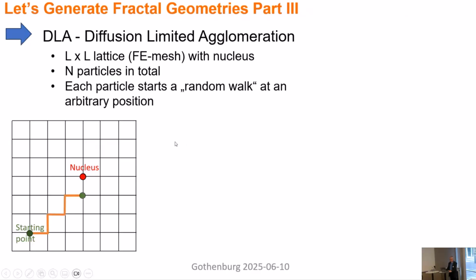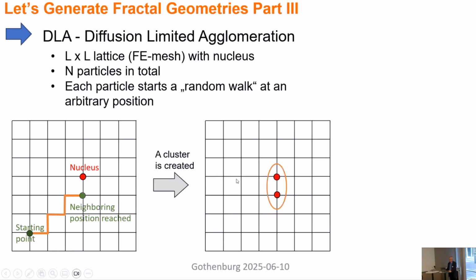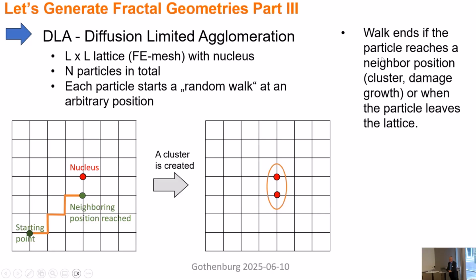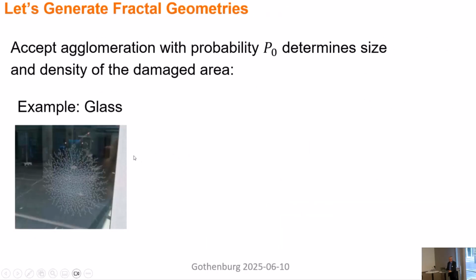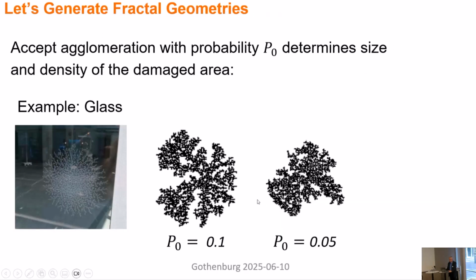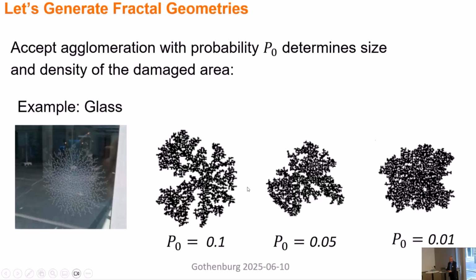And once they hit here or get closer to this nucleus, they reach a neighboring position, they stay, which means they are stopped and create a cluster. And then we start the next walker. The walk ends if the particle reaches the neighbor position of the cluster, damage growth, or when the particle leaves the lattice. And here now we can play with the probability, and if the probability is changing, the shape or the density of these patterns is also influenced by these values.